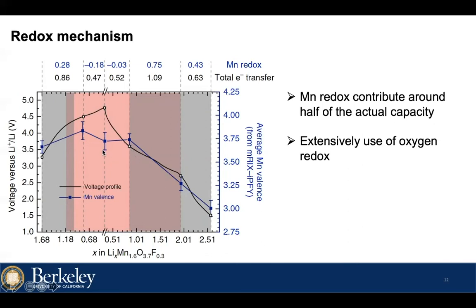And from these results and the previously mentioned qualitative measurements of the oxygen redox, we use the gray color and the pink color to mark the contribution from manganese and oxygen redox respectively. During charge, the manganese redox dominates first, and when the voltage goes higher, the oxygen redox starts to overlap with the manganese redox, shown by the gray-pink color here.